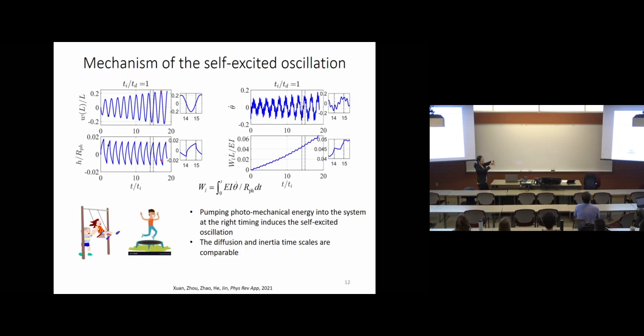So the top surface of the hydrogel shrinks, but the bottom surface still stays swollen. Therefore, it can create a positive photo moment. As you see, the photo moment starts to increase from the minimum value. By the end of this half period, the photo moment gets to the maximum value. So we can further plot the bending angle and also calculate the energy.